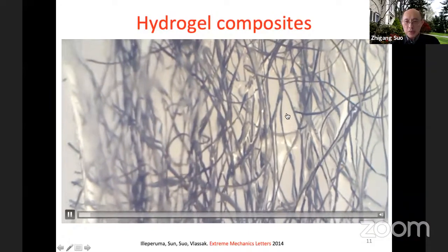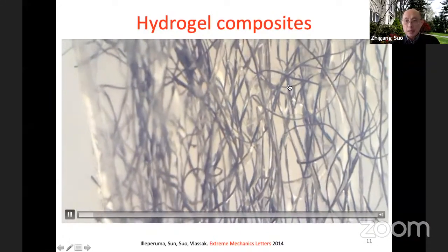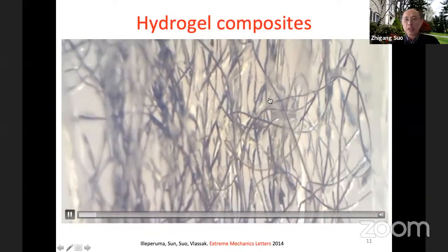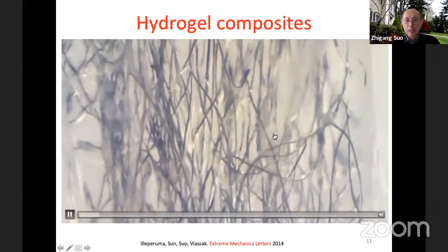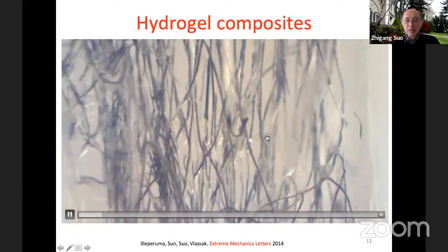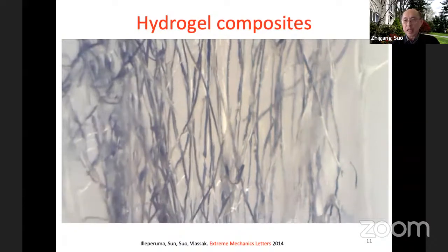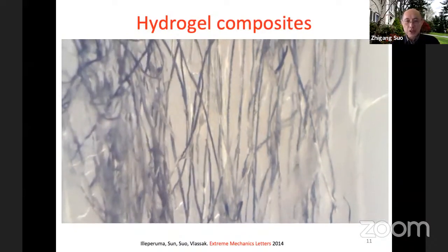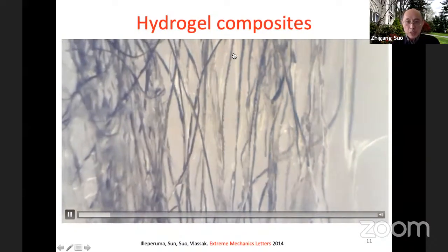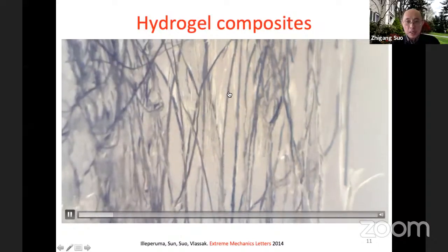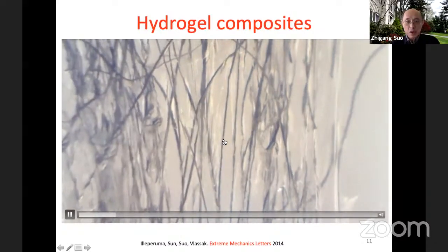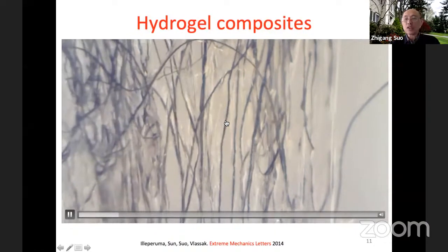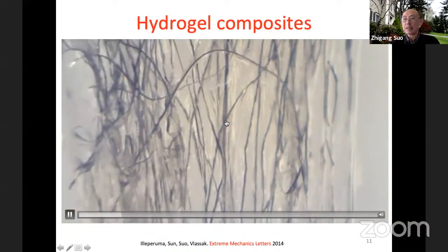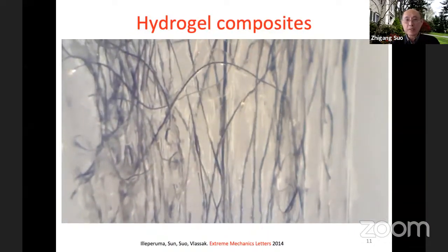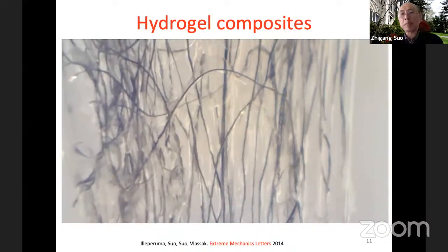The transparent thing is a hydrogel, and the fibers are just steel wires—we use steel wires, wash pots, this kind of steel wire. We put it into hydrogel. You can see when we pull this, the steel wire is streaming along. It means you have interfacial sliding, right? The interface bonding is not very good.